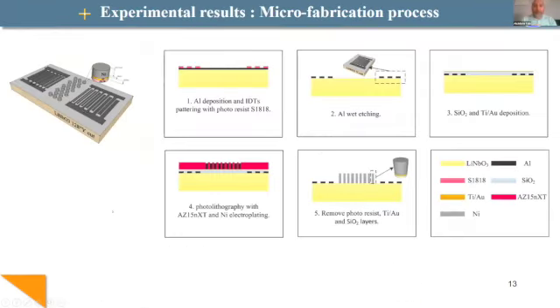We fabricated the device. The process is described here. We start with electrodes to excite, for emitter and receiver. And after we deposit some photoresist, some silicon oxide, just a small layer. And after, a titanium and gold thin layer, 20 nanometers. And after we perform photolithography with a thicker photoresist, and we electroplate nickel. After, we etch everything to get only pillars on the surface.